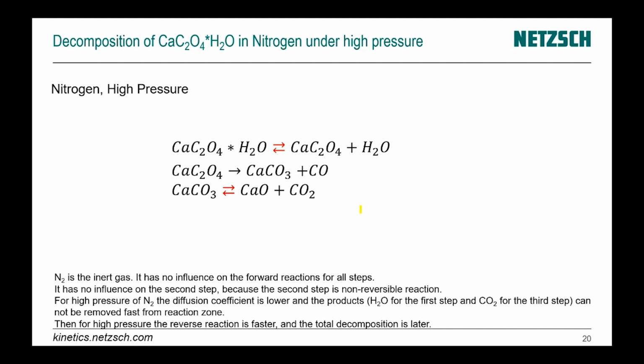If we look a little bit more in detail, then we see that the first step and the third step are reversible reactions. And it means that during the forward reaction, we have a release of some product. For example, for the first step, it is a release of the water. And then this water reacts with the calcium oxalate and produces calcium oxalate monohydrate in the backward direction. What happens with a higher pressure? For the higher pressure, we have a lower diffusion coefficient, and the water which is released during the forward reaction cannot go away from the reaction zone, and the concentration of the water is high in the reaction zone, and therefore the backward reaction will be higher for the higher concentration, or for the higher pressure of the nitrogen.